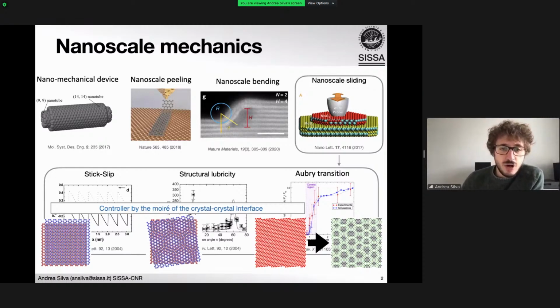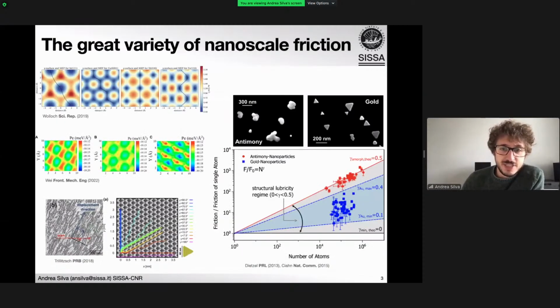The zoology and variety of these patterns and specific crystal interfaces is very big, as we saw in the talks on Monday. It can be probed by high throughput density functional studies, where you can compute the potential energy surface of two crystalline interfaces sliding. It has also been probed in experiments where, for example, in the case of antimony nanoparticle sliding on gold, the system is always pushed in the same direction, but it goes along a preferential direction due to the crystal symmetry. So there is some directional locking of the motion.